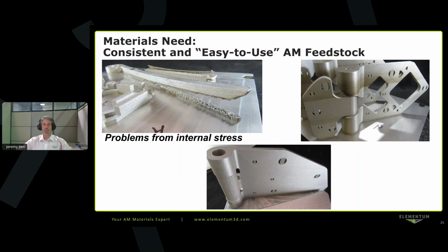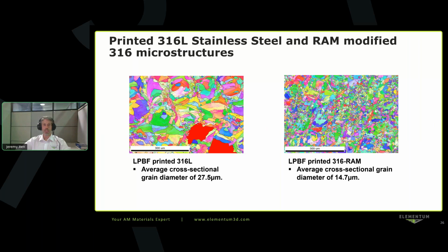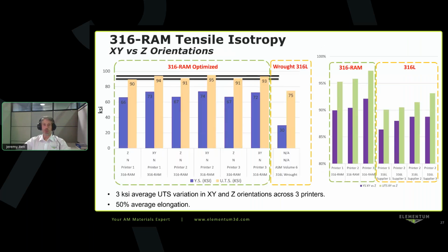So here's an example using 316L stainless steel with our modified 316 microstructure. So on the left is the standard 316L microstructure. You can see average cross-sectional grain diameter about 27.5 microns. Now our modified composition, we've cut that grain size approximately in half and made it more isotropic. Looking at material properties, the goal of this project really was to get isotropic, consistent, reliable properties in an easy to print type material.